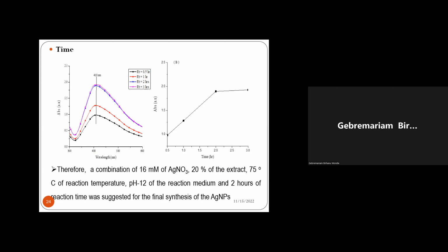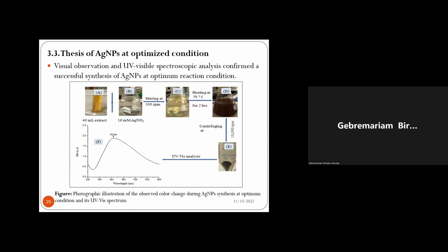So these are the conditions that were used to synthesize the final silver particles from the optimization process. We determined 16 millimole of silver nitrate, 20% of the extract, 75 degrees centigrade, a pH of 12 in the reaction medium, and 2 hours as the optimal parameters used to synthesize the silver nanoparticles. As you see, these are the different parameters, and this is the final yield after optimization. This is the amount of silver nanoparticles that we